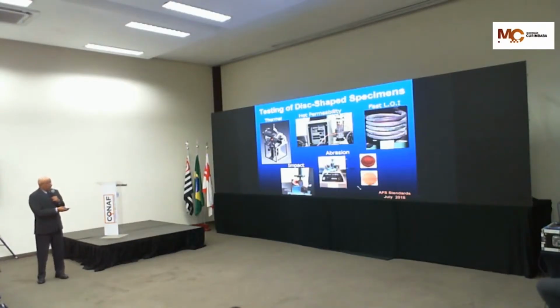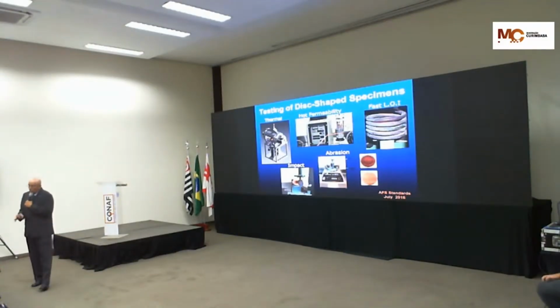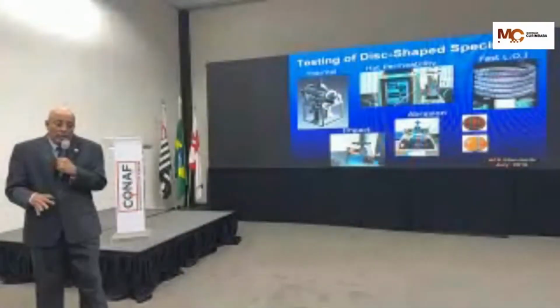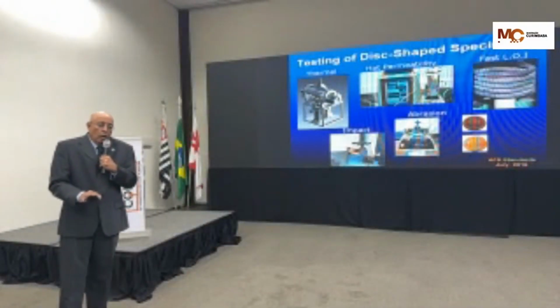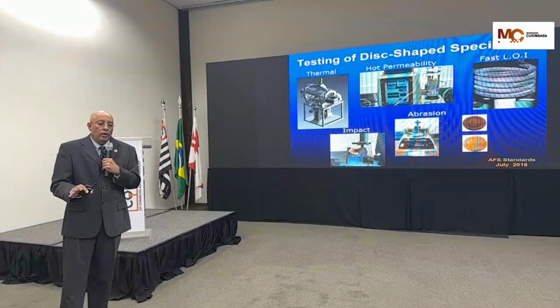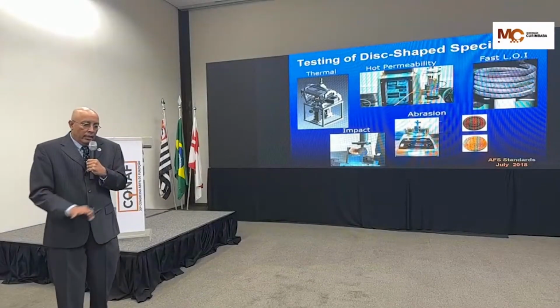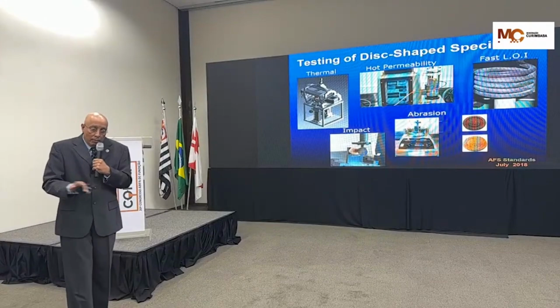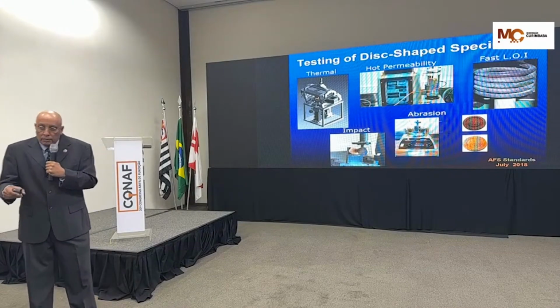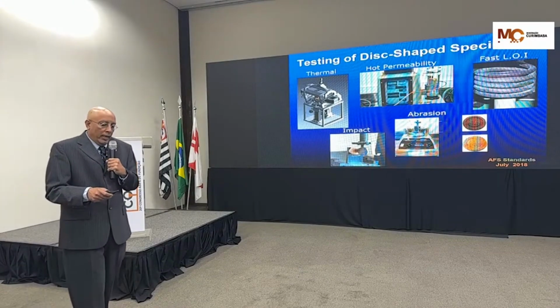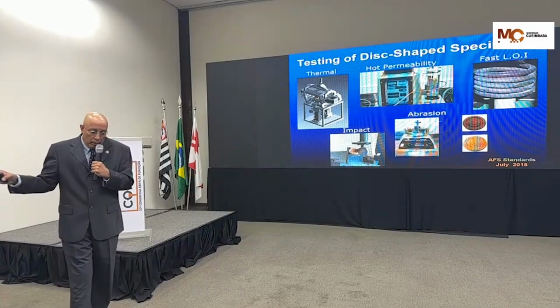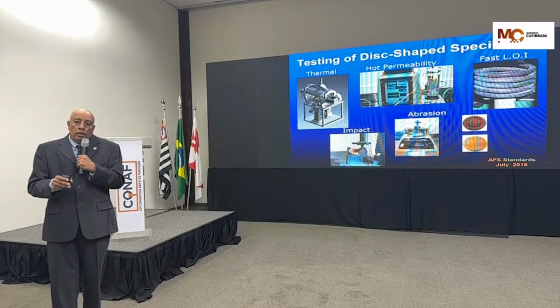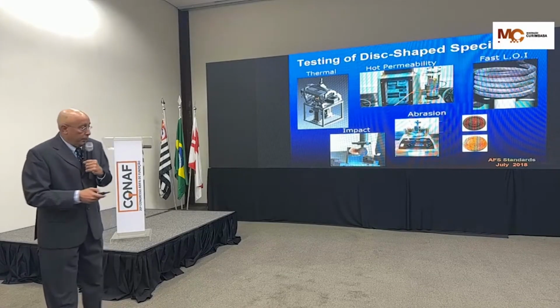The abrasion test is a test representing the friable losses or the level of cure on the sand. It is indicative of an operator rubbing his or her hands on the sand mold. And if there are erosive losses, we know where that sand ends up. If the molten metal flows in the mold, it ultimately can end up in the pattern cavity.